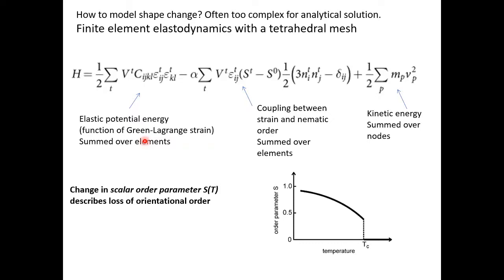What makes liquid crystal elastomers interesting is that there's a coupling between strain and nematic order. So when a liquid crystal in the nematic phase is being heated, the quality of its orientational order is described by something called the scalar order parameter. And it's a first order phase transition. It drops to 0 at the transition from the nematic to the isotropic phase. And so how much that scalar order parameter has dropped controls how much the material stretches. That's the coupling between the polymer backbone and the nematic, the molecules that are the mesogens, these molecules that form the mesophase that are attached to that polymer backbone. And so there's a coupling that multiplies the strain times the change of the scalar order parameter. And it's because this term changes that makes the whole object move when it changes temperature.